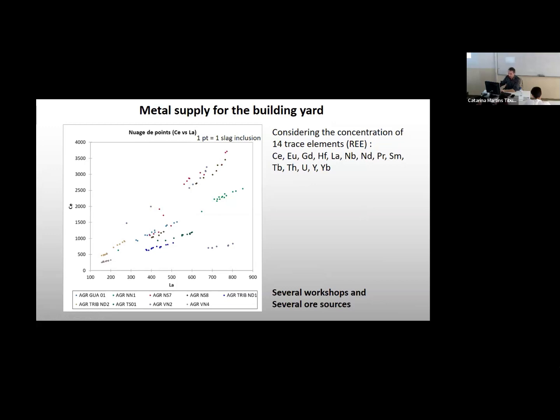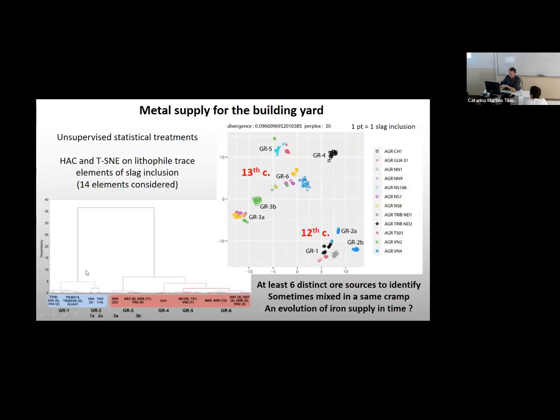And then when we mix the information about all the trunks, the 12 cramps that we analyzed so far, you see that if it came from a single workshop, you would have just a line. And here you see that you have many, many lines. That means that there are many, many different provenances. So I'm not going to go into the details, but we're using statistical means of analysis because there are many elements to compare, to try to have a better representation of the different possibilities of ore sourcing. And what we've come to so far is something quite interesting: what's from the 12th century, apart from one cramp, and what's from the 13th century seem to be from really different production zones.